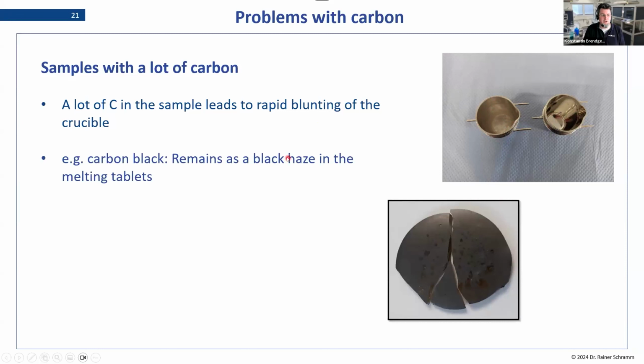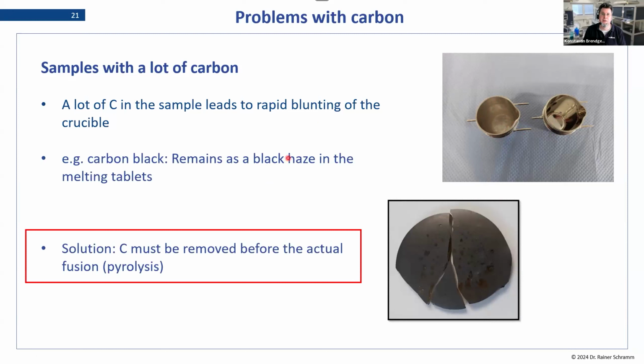So what you need to do here is get rid of that before you actually do the fusion. And it's pretty simple, by just doing what we call a pyrolysis. You don't mix the sample in your flux, you put it on top, and then you do a low temperature step to burn away the carbon, and then you ramp up to the fusion temperature. That usually works fine with samples containing carbon and also samples that contain a lot of organic materials. We need to get rid of that before we actually do the fusion.